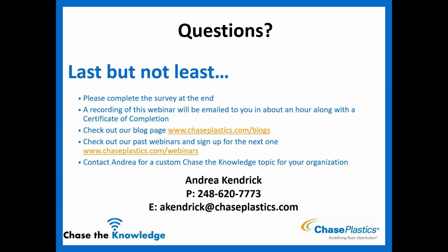And then Mike, I see we got some back and forth here on the carbon black. Let's take your question offline to see if we can better describe what we're seeing in terms of carbon black and its UV absorbing tendencies. Thanks as well to the rest of the team. Got some input here from one of the attendees, Mike, who chimed in on the size of the particle for carbon black. The rationale for smaller particle sizes being chosen is that you get more surface area of the carbon black to convert UV to heat, and that 19 nanometers is typically regarded as a good compromise to avoid agglomeration, as smaller particles are prone to. So thanks, Mike, for the additional input for the rest of the group as well.